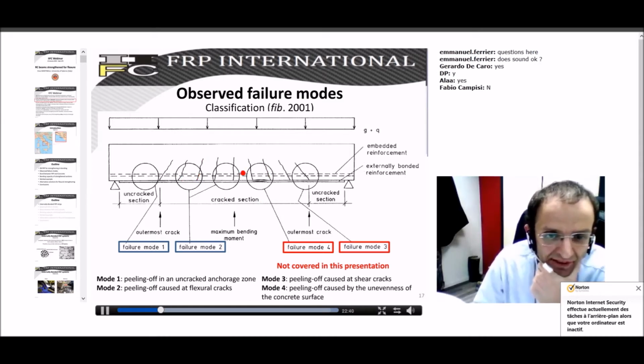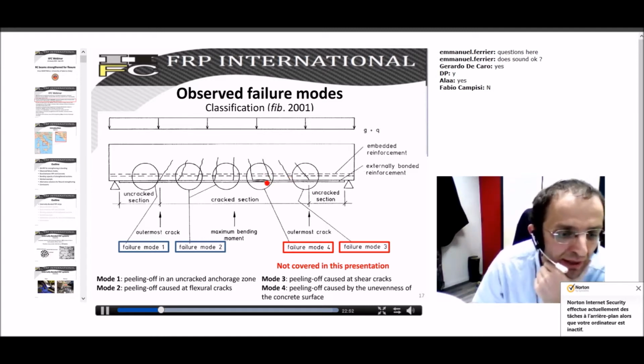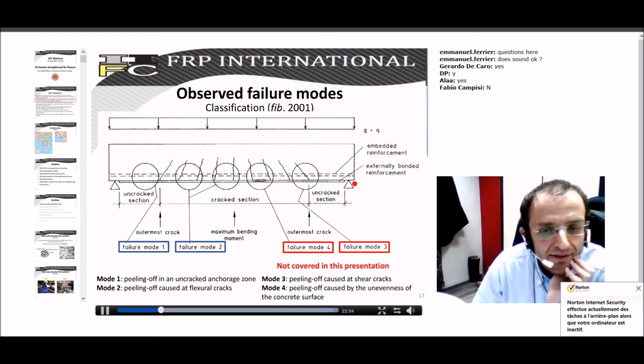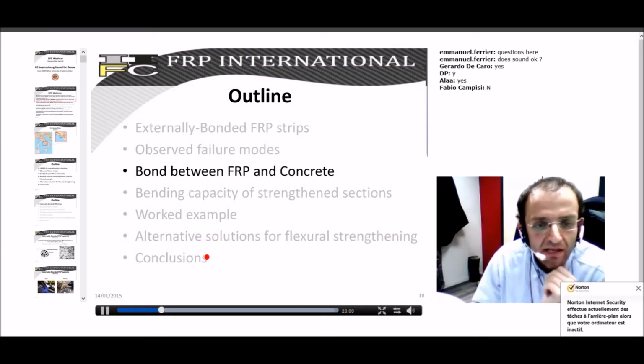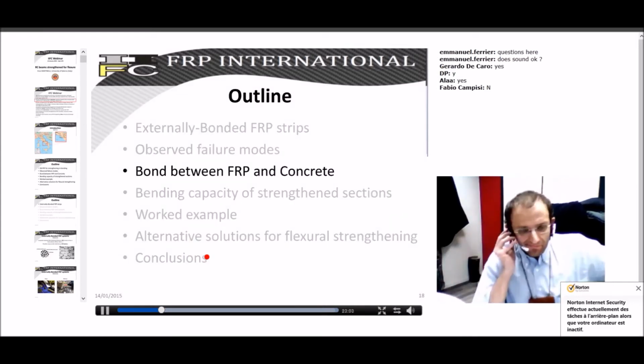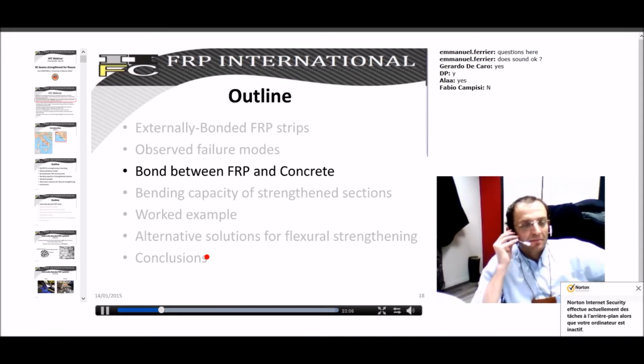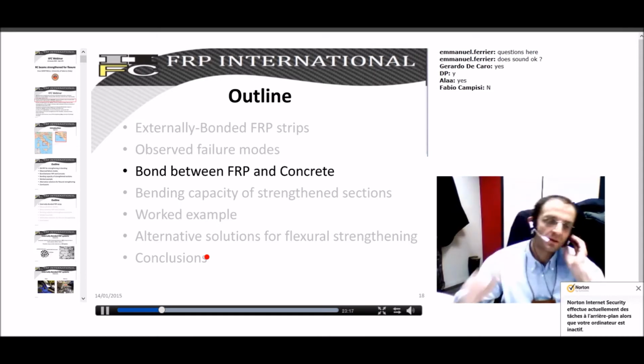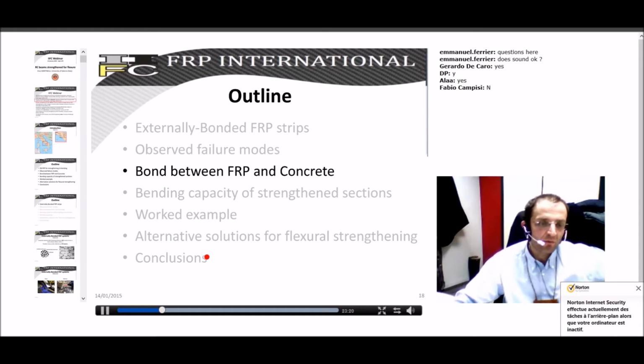There are other failure modes which are due to defects or which are due to shear cracks, which will not be explicitly covered in this presentation because the defects usually are covered by safety factors, and as I said, the shear strengthening is not part of this presentation. So as you see, these new failure modes are generally controlled by the bond which develops between the FRP strip glued to concrete and concrete itself. So we have to investigate and we have to understand how bond works.